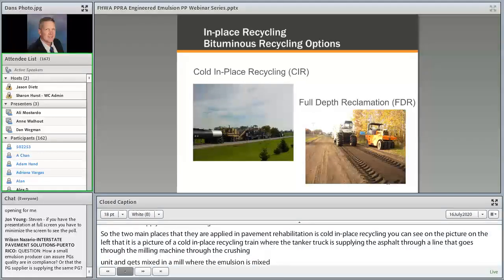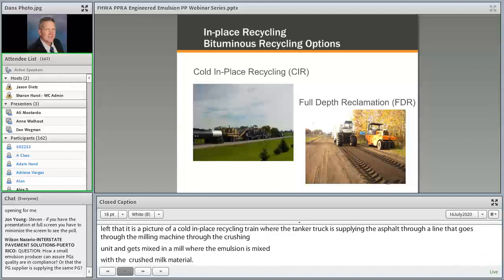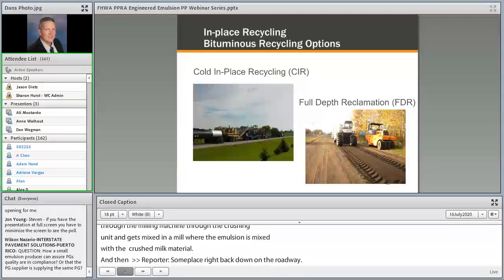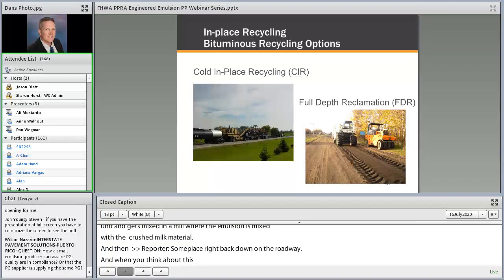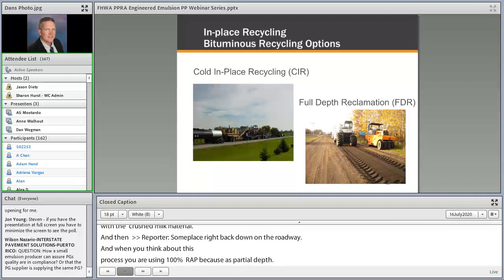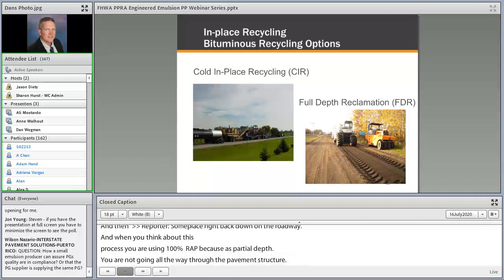And when you think about this process, you're using 100% RAP because it is a partial depth process. You're not going all the way through the pavement structure. The reason for that is you need to support that heavy train as you're going down the road. So if you take too much of that pavement structure off, you can end up breaking through the pavement and causing problems with the laydown.